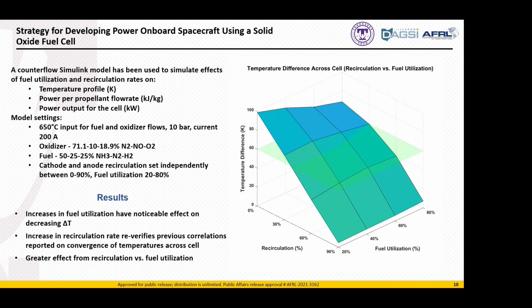What kind of catalyst will produce this? Because this is essentially the bottleneck of applying this solid oxide cell. If you cannot decompose the nitrogen tetroxide effectively, then you have a problem of corrosion on your cathode. Nitrogen tetroxide is highly corrosive. So before you can expose your cathode to an oxidizer, you have to really reform this oxidizer to a perhaps less reactive mixture, such as nitric oxide and oxygen.